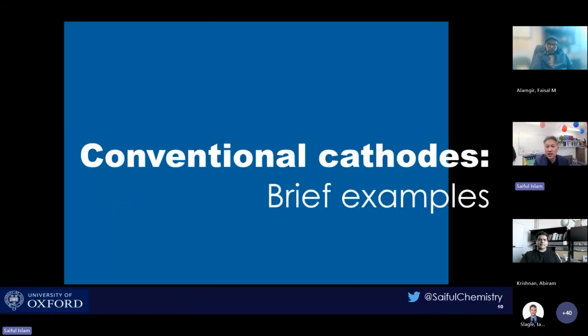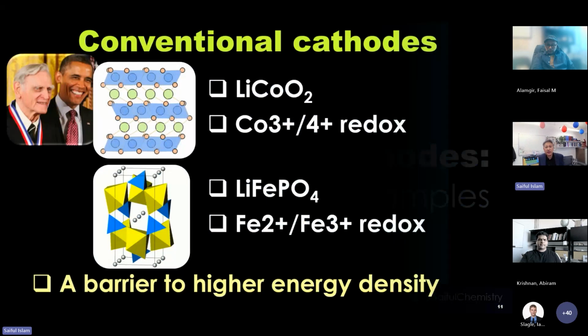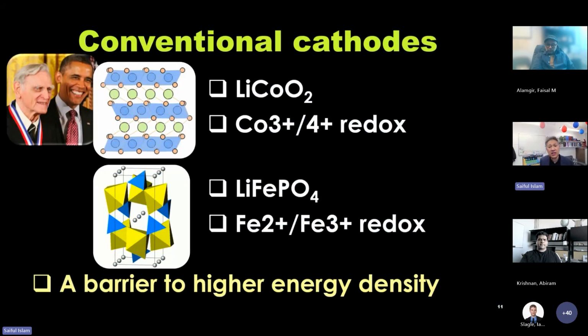So let me start on the main course and start off on conventional cathodes, a couple of brief examples. So the conventional cathodes are based on two main materials. The first one is the layered oxide, lithium cobalt oxide, which has a redox process of 3+ and 4+ largely. And that material, in a way, dominates the portable devices that we use. There might be variations of cobalt oxide, but they are dominated. Below that is lithium iron phosphate, which has an iron 2+, iron 3+ redox couple. And the structure is shown on the left, where you've got yellow octahedra, which are the iron octahedra, and the phosphate groups in blue. And that is the olivine structure.